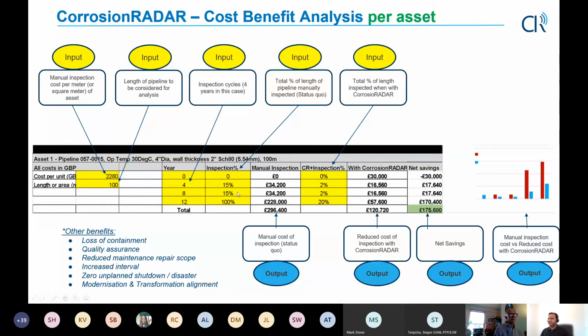So with the usual inspection cycles of say 10 to 20% of inspection every few years, 4 to 5 years, and in 12 years 100% is stripped. So can we reduce that extent of insulation strip by putting a monitoring system, and over the overall lifetime the saving is about 60%, and depending on the asset it can vary from probably 30% all the way till 60%, depending on the criticality of the asset and the costs involved in inspections, etc. We tend to get involved with that. So that's a typical range, 30 to 60%.